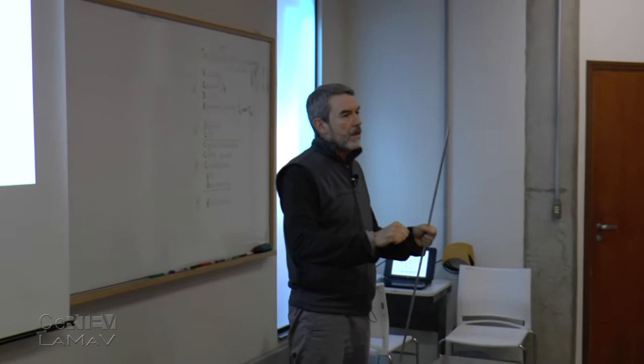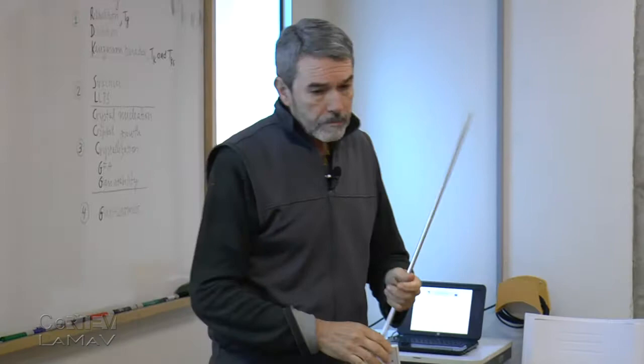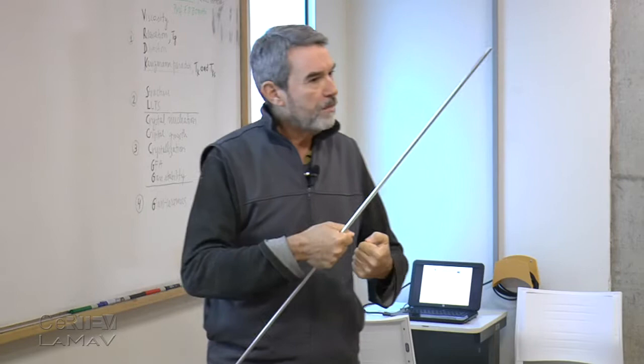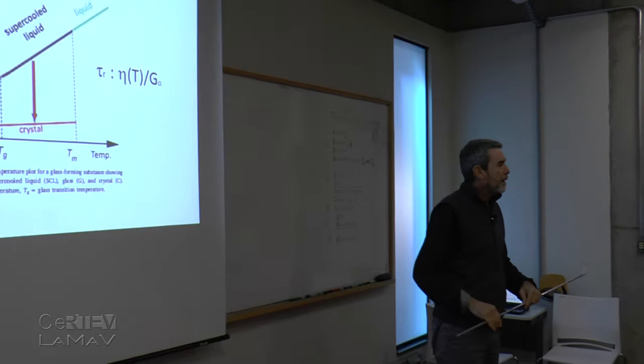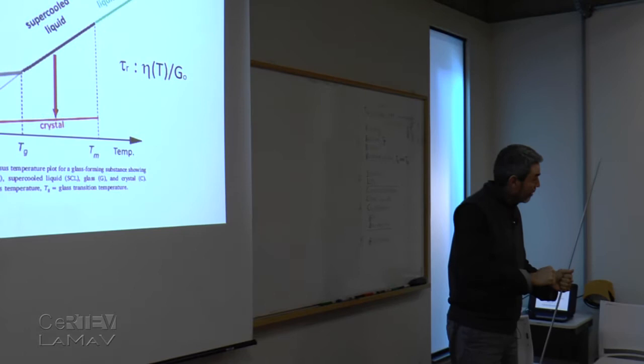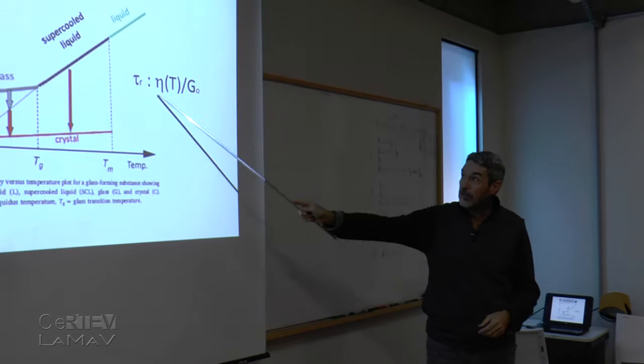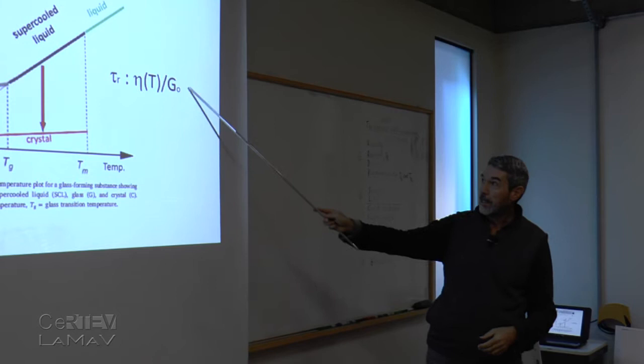At very high frequency of mechanical strain-stress measurements, at infinite frequency, you can calculate the shear modulus. So it's almost temperature independent, because it's calculated at very high frequency. But the viscosity is temperature dependent. This ratio, the physicist Maxwell came up with this ratio, is a measure of the characteristic relaxation time.